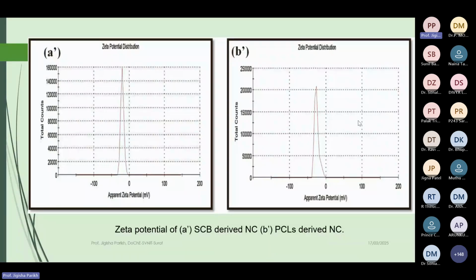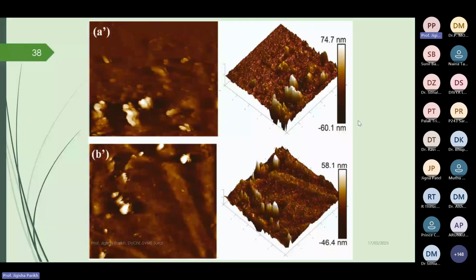Similarly, another parameter was identified by atomic force microscopy, which shows the 2D and 3D images of both the derived nanocelluloses. It shows that a long fibril structure in these images has been identified. And this indicates that the chemical and mechanical treatment eliminated the cementing components, particularly hemicellulose and lignin, around these fiber bundles. So this confirms the removal of hemicellulose and lignin from this nanocellulose, and validates the formation of very good quality nanocellulose crystals.